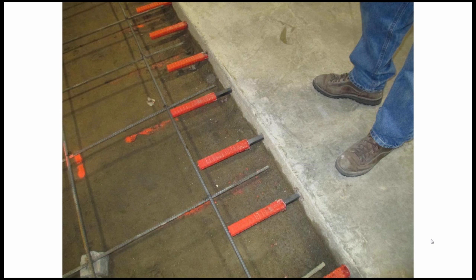So at this location, we have a square dowel with a rectangular slip sleeve that goes over the top. What this does is allow movement in the horizontal plane. So when that new slab shrinks, and the existing slab, of course, isn't going to have those shrinkage strains, it doesn't create a lot of shrinkage stress because we allow the movement in the horizontal plane, but it doesn't allow movement in the vertical plane.